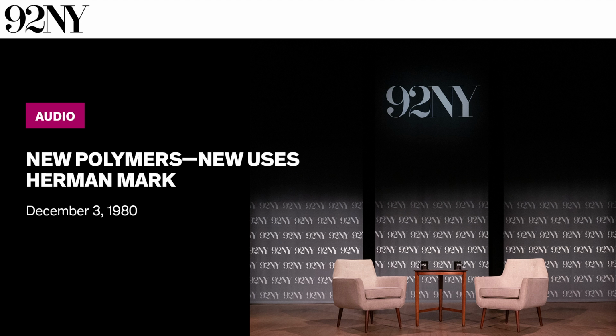What is being done, for instance, is the following. You take this fabric, which is being cut in ribbons of this width. Then these ribbons are run through a thermosetting resin, and they are imbibed with a thermosetting resin. Then they are wound around a mandrel, 1 ply, 2 plies. Then the resin is set, and then the whole thing is carbonized. And then you get pipes, you see? Pipes of this type.